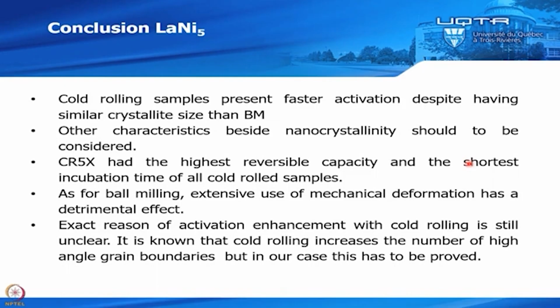Okay, so cold rolling 5 times has the highest reversible capacity and the shortest incubation time of all the cold roll samples. For ball milling, if you ball mill for too long, it has a detrimental effect, so it's not good to ball mill for too long and to try to reduce the crystallite size to very, very small. Sometimes it's better to have a crystallite size that is a little bit bigger, but you still have faster kinetic.